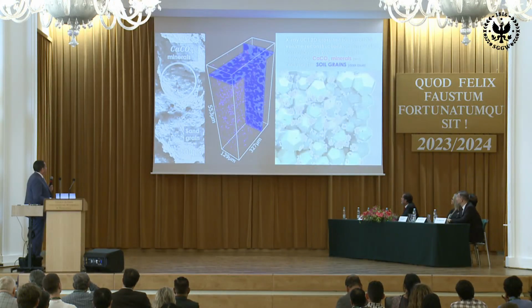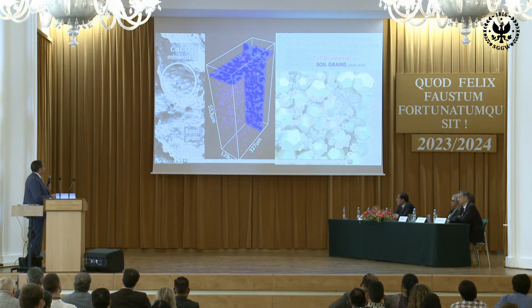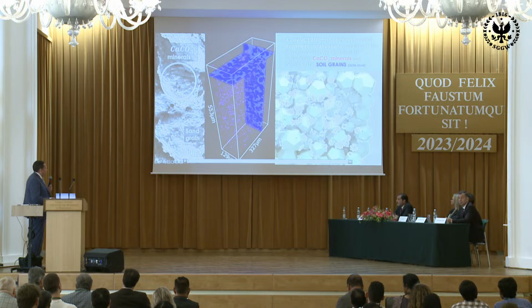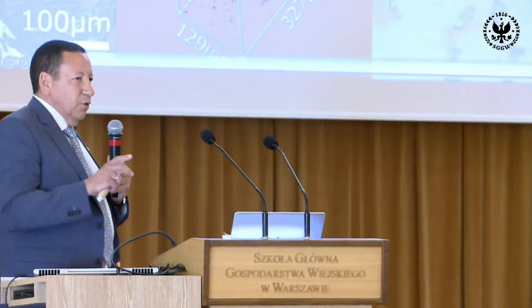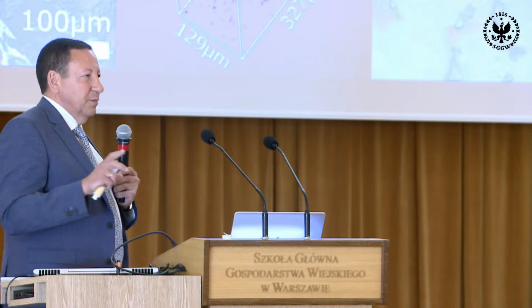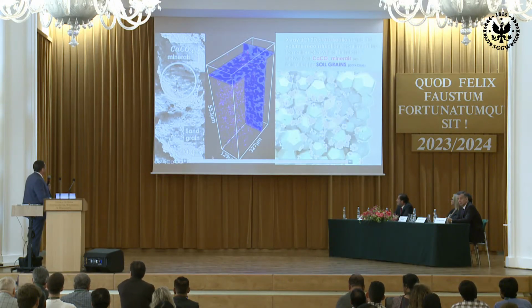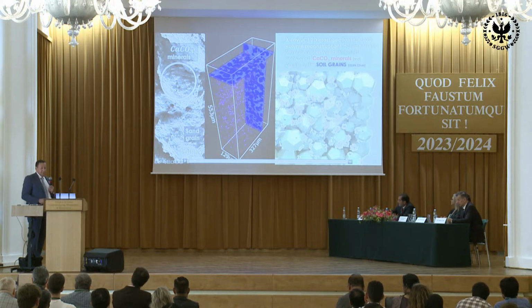So here you see the result of a sample. This is almost like a triaxial sample size. What you see here in blue are the soil grains. In red are our CaCO3 minerals. And you see that we get exactly what we expected in our video. So we have a homogenized distribution of our calcium carbonate inside the ground. And if you go to another scale, here 100 micrometer, you can see our sand grains, and you see the precipitation of calcium carbonate minerals.